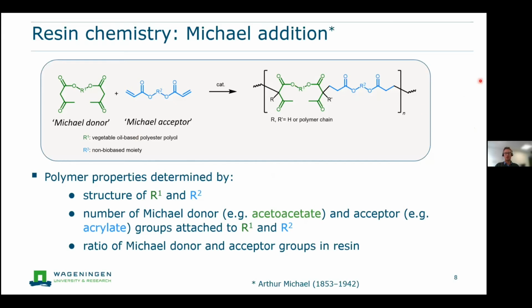So to zoom in a bit on the chemistry that we used for this application, this is a so-called Michael addition chemistry. And it is depicted generally here. So in Michael addition chemistry, if you want to make polymers, you need a Michael donor, which is multifunctional. So look at the end groups here. And you need a so-called Michael acceptor, which also has at least 2 reactive groups. And together they react already at room temperature. And they give long cross-linked polymer networks.